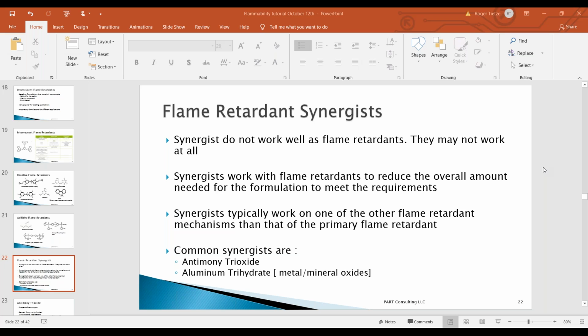The synergists typically work on one of the other flame retardant mechanisms. So antimony trioxide is one example, aluminum trihydrate is another. If you combine bromine or phosphorus with aluminum trihydrate, you get a char, but you also reduce the heat release. So that's what makes them so effective, the fact that they attack the fire in more than one way.